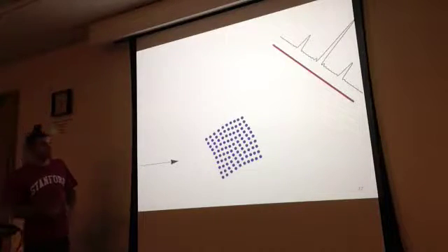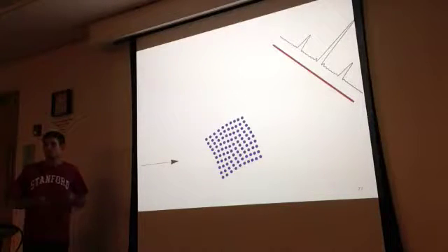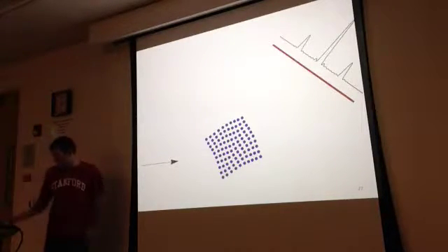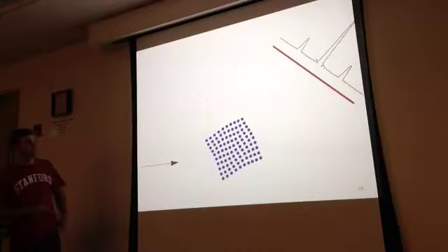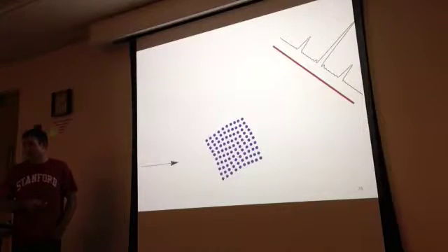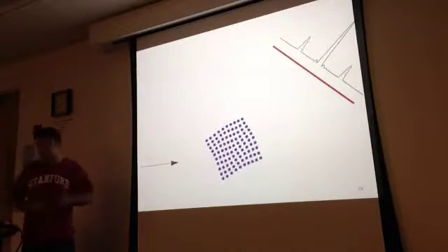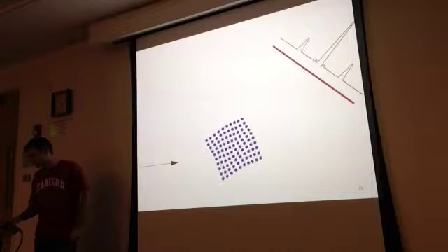The reason for that is the height of these peaks is proportional not to the phonon displacement, but to the phonon displacement squared. A consequence of that is that if we now let these ions go and oscillate, the ions will be oscillating at the phonon frequency, but these side peaks will be going at twice that frequency. So there's a factor of 2 discrepancy, and this will come up again.